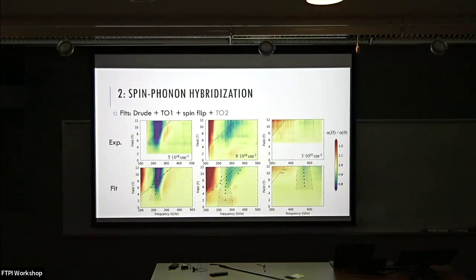But the most obvious effect by far is the narrowing. So this blue here means that intensity goes down, which if you calculate the reflection coefficients from the dielectric functions means that the phonon essentially narrows.